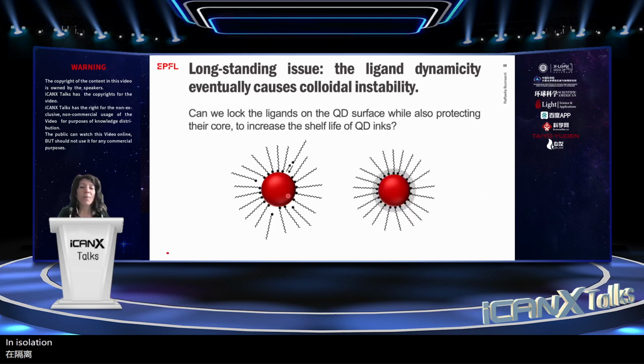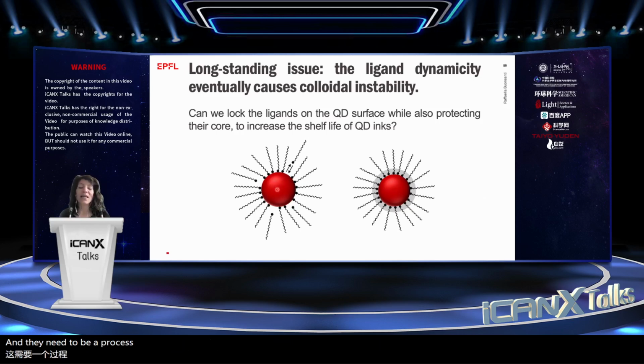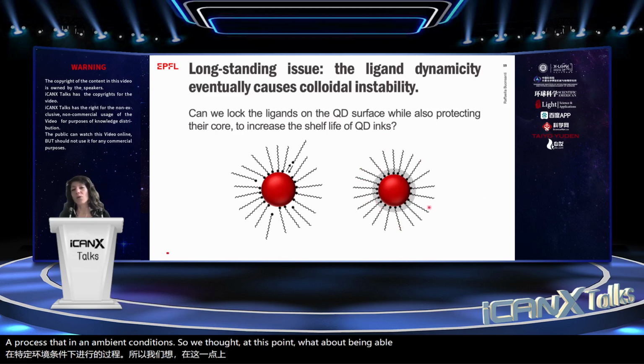And also, many of these luminescent quantum dots are really sensitive to moisture or to oxygen, and they need to be processed in an inert atmosphere. That, of course, can be done, but it would be much more convenient to have them processed in ambient conditions. So we thought at this point, what about having an oxide shell which protects the inner core and also locks the ligand on the surface, so that we are able to make colloidally stable inks and to increase, in general, their shelf life.